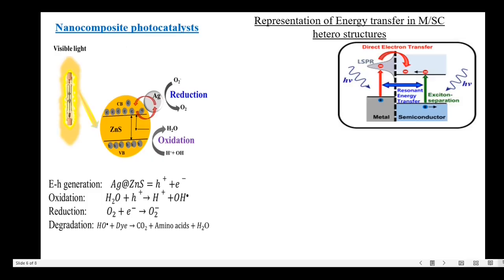Let me talk about nanocomposite photocatalysts. Photocatalyst materials convert toxic components into non-toxic components and find major applications in environmental purification. Most semiconductor nano-photocatalysts show a drawback of faster electron-hole recombination. However, the preparation of metal-semiconductor nanocomposites can enhance the catalytic efficiency of the semiconductor nano-photocatalyst. For example, taking Ag-decorated ZnS nanocomposite under visible light irradiation, electron-hole pairs are generated: holes are involved in oxidation reactions and electrons in reduction reactions. After degradation, dye molecules are decomposed into CO₂, amino acids and H₂O — that is, toxic components are converted into non-toxic components. This process is called photocatalysis.